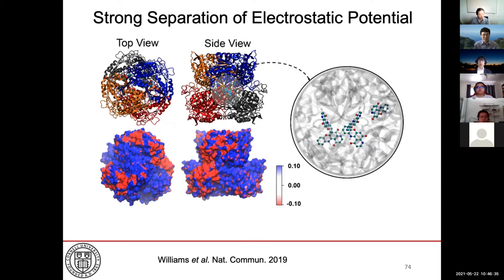So given this very, very clear separation in the electrostatic potential, we can conceive of a mechanistic pathway where the individual tetramers could coacervate, where the blue regions come into contact with the red regions to form a protein-pigment superstructure. And right now, we are probing this using coarse-grained molecular dynamics simulations.